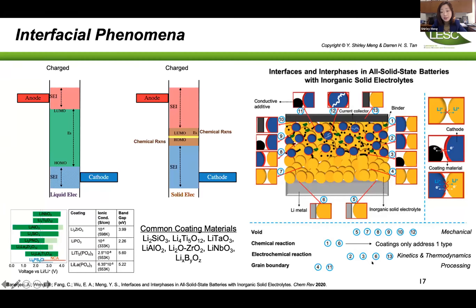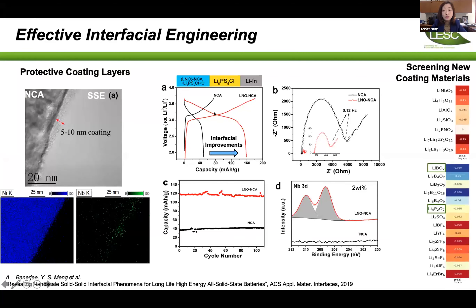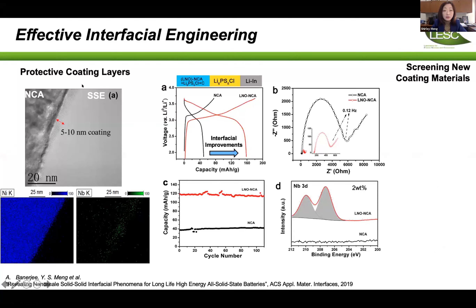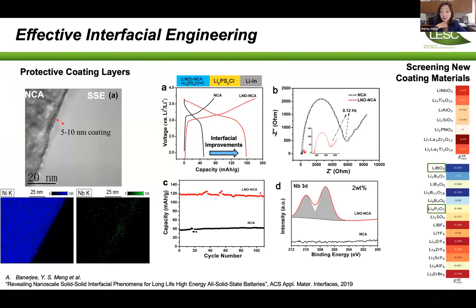The SEI problem becomes more complex with mechanical incompatibility between electrode and electrolyte materials. We wrote a review on this: if cracks or voids form due to mechanical incompatibility — because you're moving lithium metal in and out — you create many more interfaces compared to the liquid system. The lithium niobate coating example that Dr. Sun showed has been reproduced by many groups: without protection of the cathode against the sulfide electrolyte, you can't even activate the materials, but with a protective layer, performance is much better.